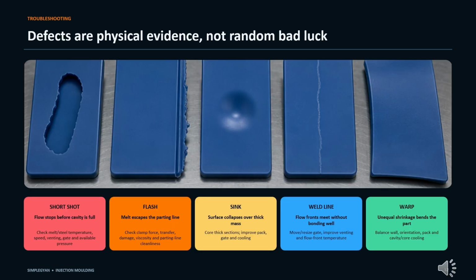A defect is a clue to the physics that went wrong. A short shot means the flow front stopped before filling. Investigate temperature, speed, venting, gate restriction, and available pressure. Flash means cavity pressure exceeded the mold's ability to stay sealed, or the parting line is damaged or dirty. Sink usually traces to thick mass, insufficient packing, or uneven cooling.